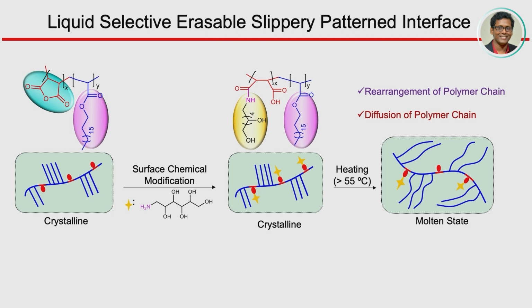So our postulate is like this. We have a crystalline network that has a limited amount of this maleic anhydride group that is reacting with this glucamine, and it cannot really go deeper inside, right. So whatever is available on the surface, that is getting modified, and when you are heating up in the molten state, it undergoes some sort of reorganization or diffusion, right, and that helps to reorganize the chemical function on the top, because naturally any surface you keep, it always wants to keep the top surface free energy low. So if they have availability of some sort of functional group which is not like glucamine, it will be exposed out, and that's the way we see further dominance of this maleic anhydride group.